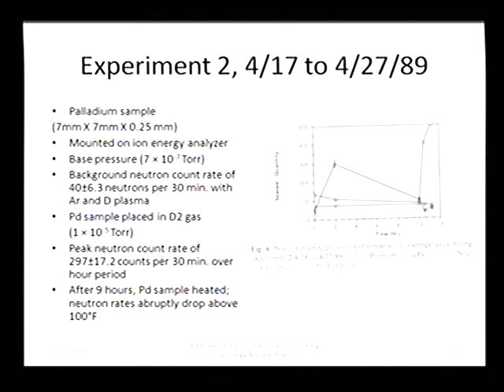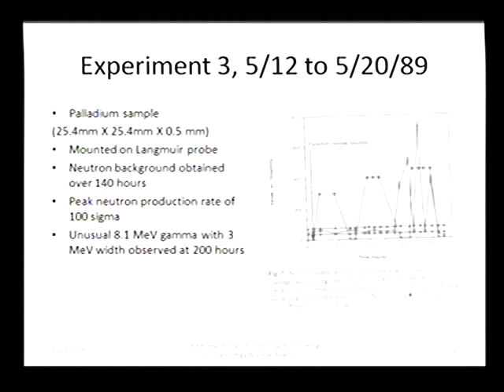After about 9 hours, the palladium sample temperature rose, and then basically neutron count rates abruptly dropped above 100 degrees Fahrenheit. The third experiment was done with a mounted Langmuir probe, and we did both plasmas and just variation of gas pressures in this particular setup. We basically did very long counts here. We had a peak neutron production rate that was about 100 times sigma of background.